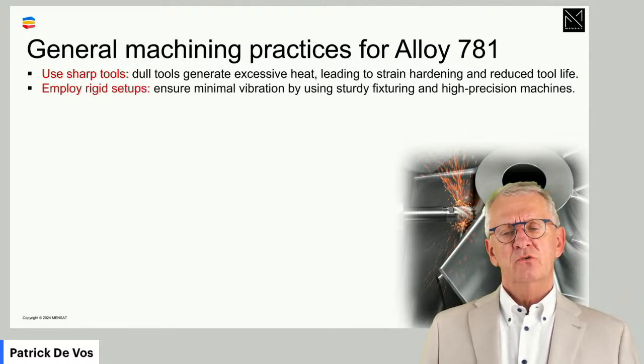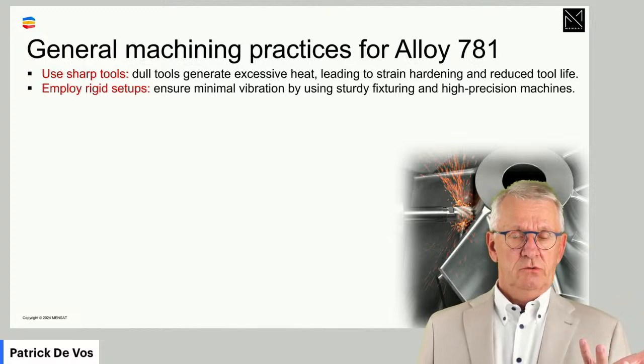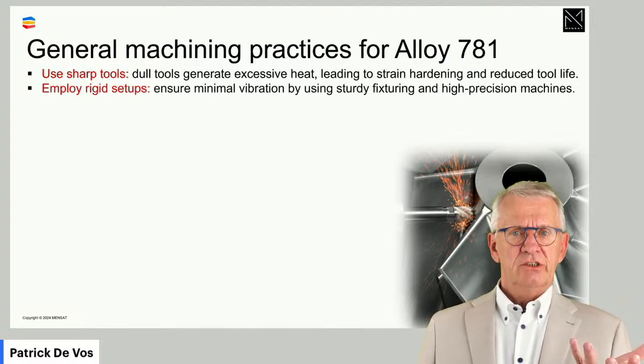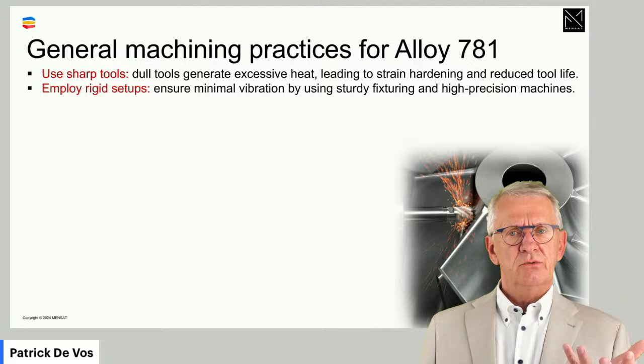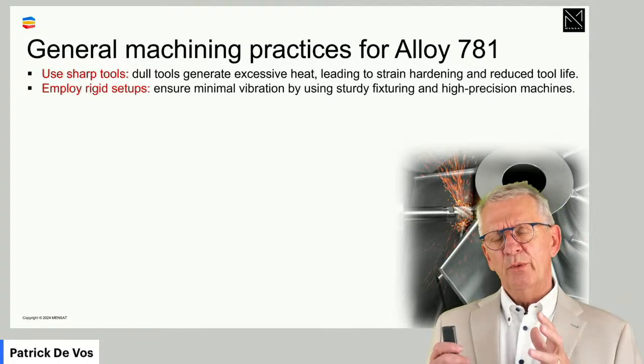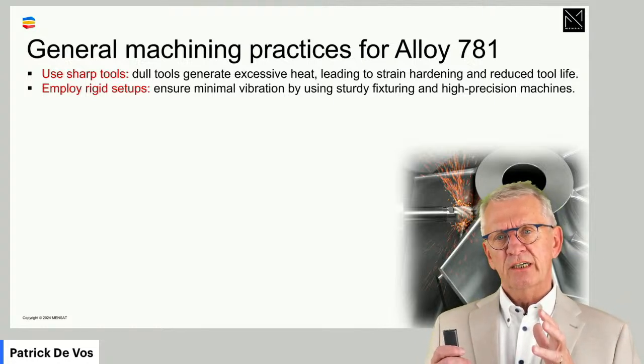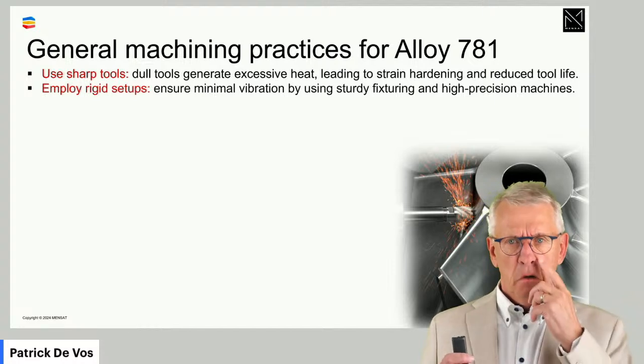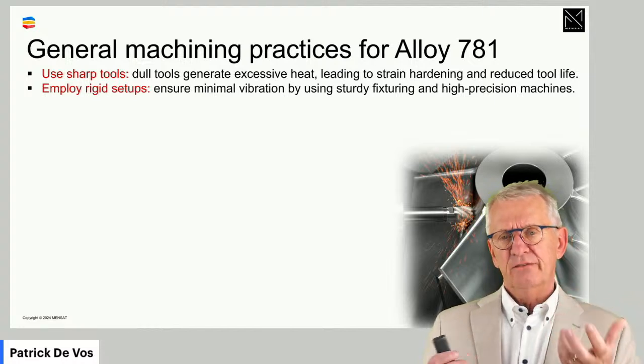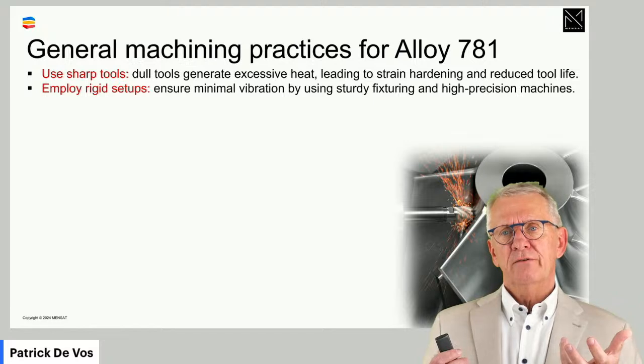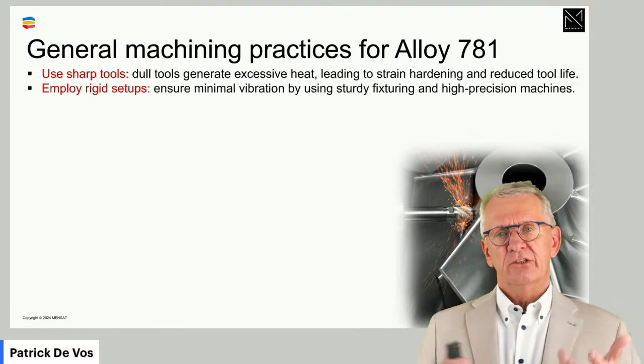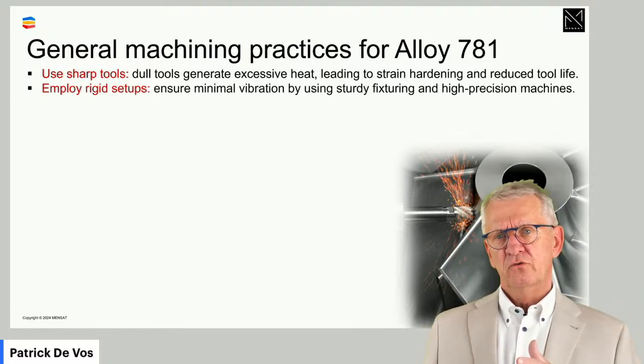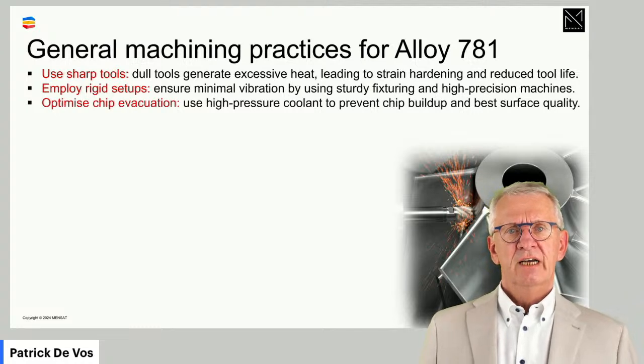Make sure the tool is working, because you have a sharp tool, in stable conditions. Avoid micro vibrations, in other words, because that's the weak part of a sharp cutting edge. It's sensitive to micro vibrations. It's sensitive to too high cutting forces and too big variance in cutting forces. We have to take care of that.